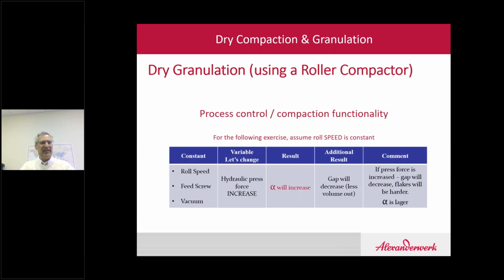Let's assume the roll speed is held constant, the feed screw is constant, but the vacuum is also constant, and I increase the hydraulic press force. Just like on Rob's tablet presses, if I increase the press force, I'm densifying the material more. I'm squeezing it harder. So what actually happens is the gap decreases.